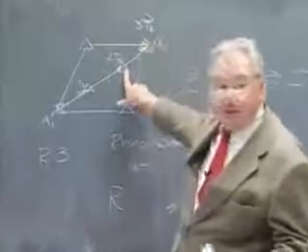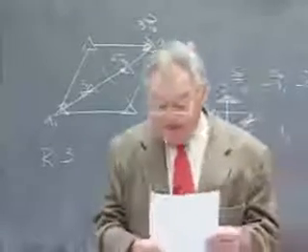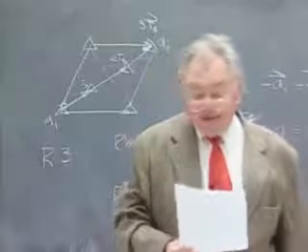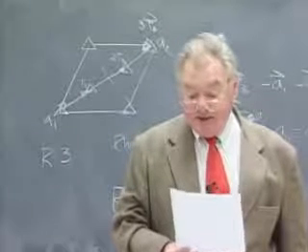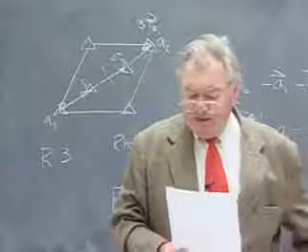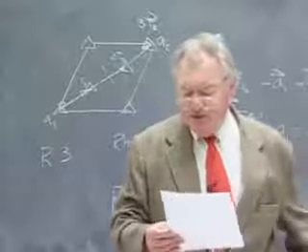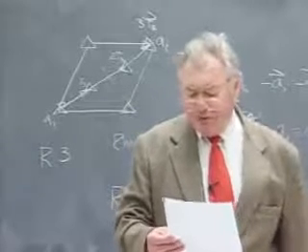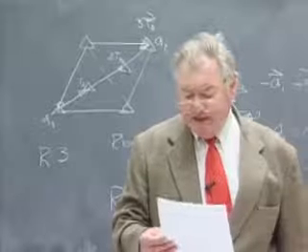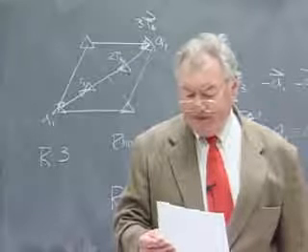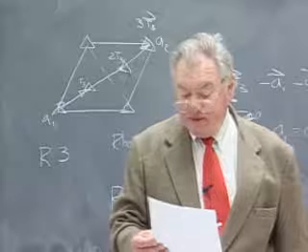So I cannot have a rhombohedral lattice for P6 or P6mm. The primitive hexagonal lattice is the only thing that works. And then we have this curious situation with the two alternative settings of point group 3m in a hexagonal net, P3m1 and P31m.